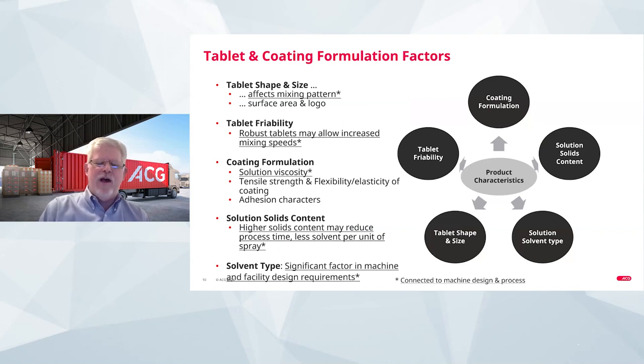handle your R&D scale, but when you get up to production scale and dealing with 400 kilos in a drum, can the tablet itself withstand the mechanical stress of the coating process? And then looking at your coating formulation, and I know this is much more in Shantanu's area, but looking at the viscosity of your solution, ensuring that we can effectively spray that and atomize it effectively. And then looking at the coating formulation from a tensile strength, flexibility, adhesion characteristic onto your tablet. And finally, also looking at the solids content.